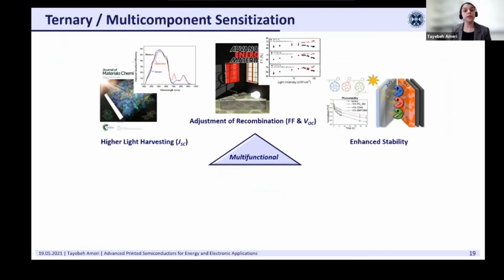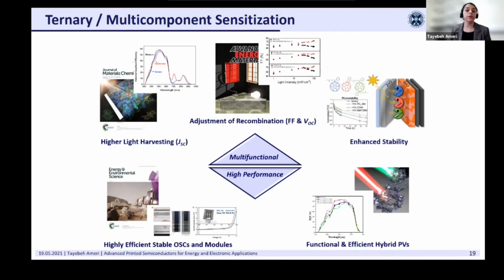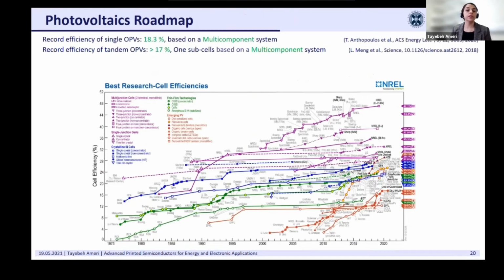So far, I hope that I could show and convince you that we have developed a multifunctional concept called ternary or multi-component sensitization, which not only increases the light harvesting and short circuit current, but can also adjust the recombination mechanism and improve the fill factor and open circuit voltage, and have a significant influence on the stability of our devices, leading to highly efficient and stable organic as well as hybrid solar cells and modules. And honestly, as a person who spent over 6-7 years on the development of this concept, it is my pleasure to see that nowadays this multi-component concept is the leading strategy in organic photovoltaic technologies, and based on it we have over 18% efficiency, which is just a great value and progress in this technology.